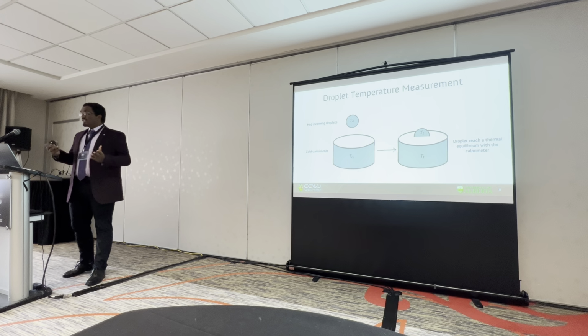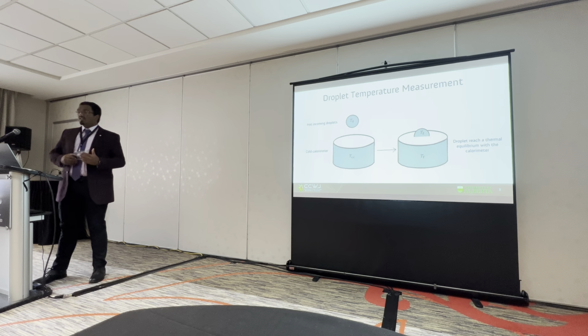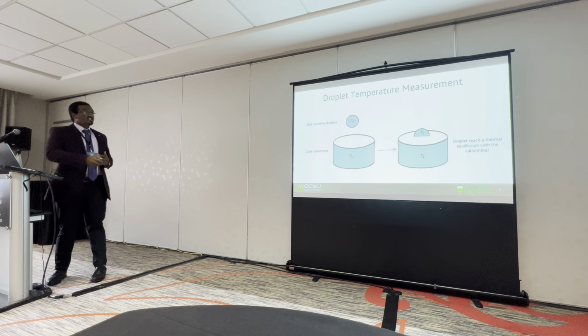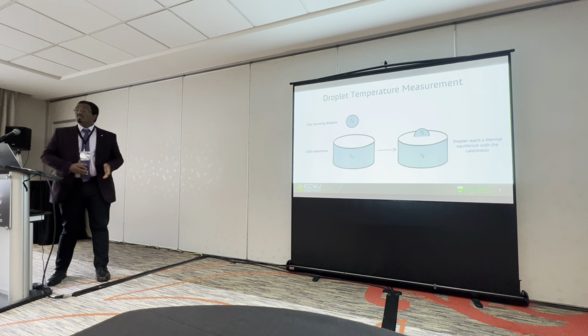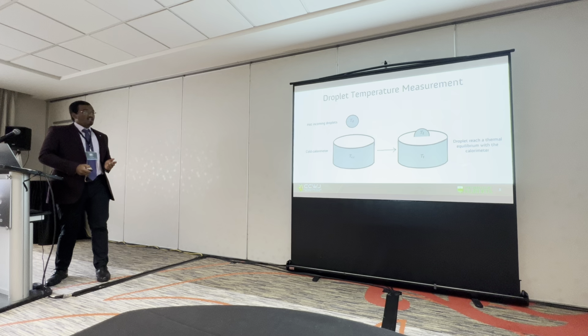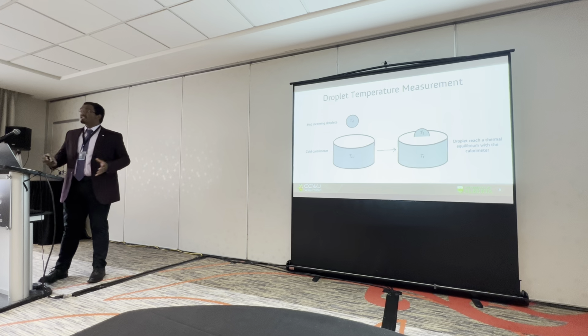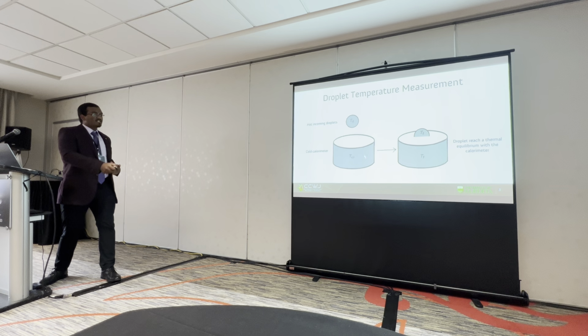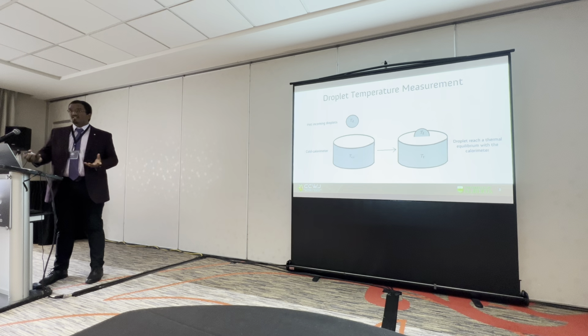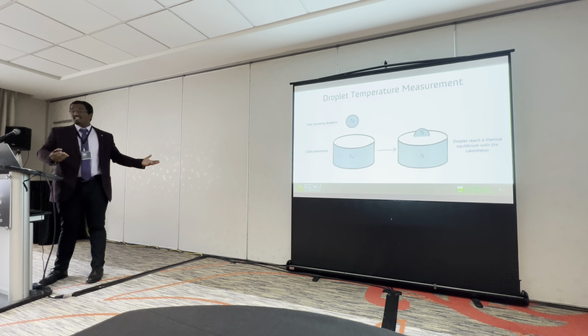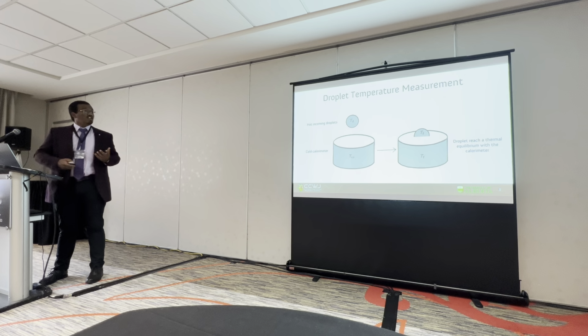So the way we do our droplet temperature measurement is based on a mass and energy balance from the initial phase, in which the hot incoming droplets fall into a cold calorimeter, to the final stage, in which the droplet and the calorimeter reach thermal equilibrium. These two stages are selected in such a way that any stage in between can basically be ignored, because in a mass and energy balance, nothing is lost. So from the initial stage to the final stage, it gives us a very good estimate of the droplet temperature.